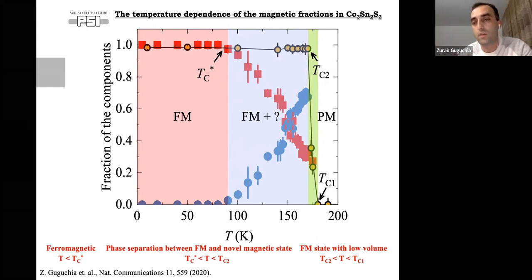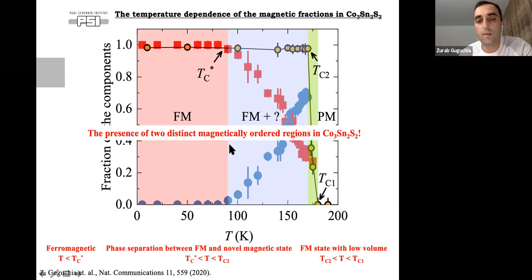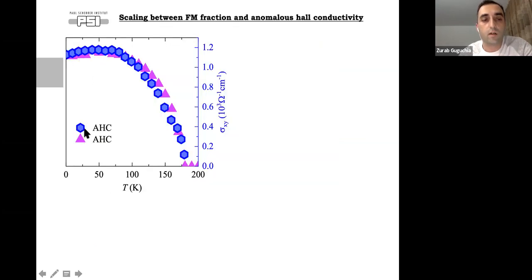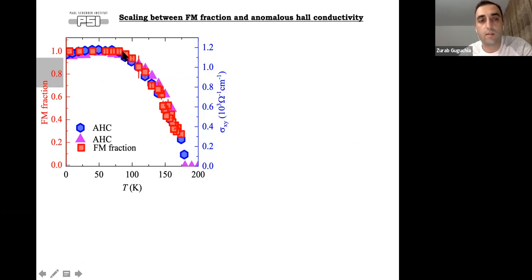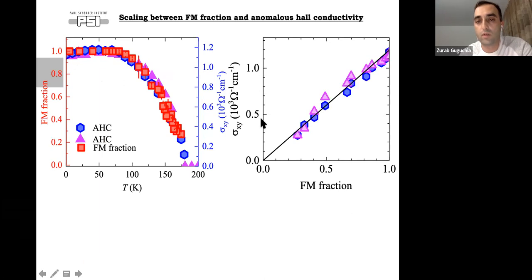But now we of course need to understand what the second magnetic state is. But before I address this question, I want to show you already what type of correlation we have between these two distinct magnetically ordered regions and the topological Hall effect. So here I plot this anomalous Hall effect measured on two different samples. They match nicely to each other. Now, if I plot the ferromagnetic fraction on top, you see clearly that the temperature evolution of the ferromagnetic fraction scales very nicely with the temperature evolution of the anomalous Hall conductivity. And I can also make this plot of conductivity versus ferromagnetic fraction, and you get a very nice linear correlation between these two quantities.